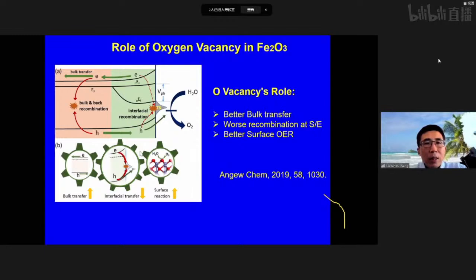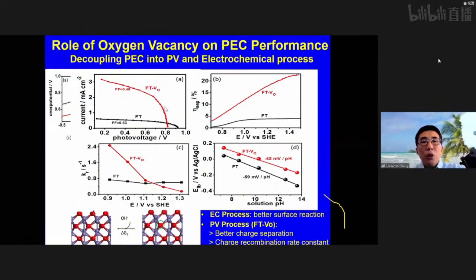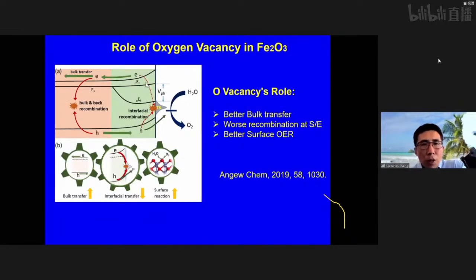But on the surface, in the oxygen evolution process, the kinetics can be faster after introducing the oxygen vacancy. But in the middle, that means the interfacial area, because we introduced the oxygen vacancy, which will behave like some trap state. It blocks the split of the Fermi level, the Fermi level that is related to the VOC. As I said, here VOC is decreased. Because of the reduced VOC, the driving force for the charge separation is not that significant. In this case, on the surface, the oxygen vacancy plays a detrimental role.